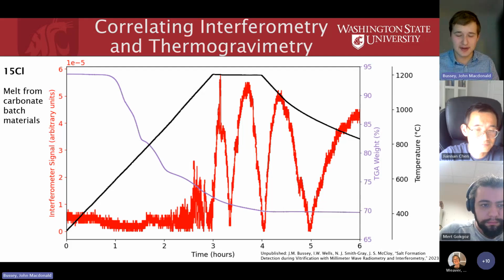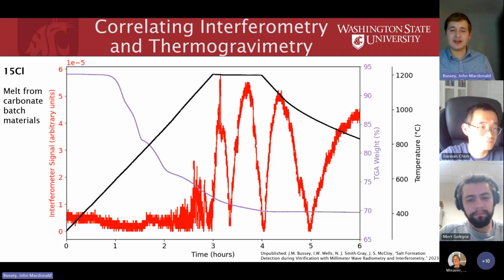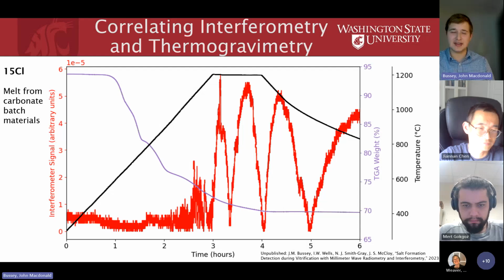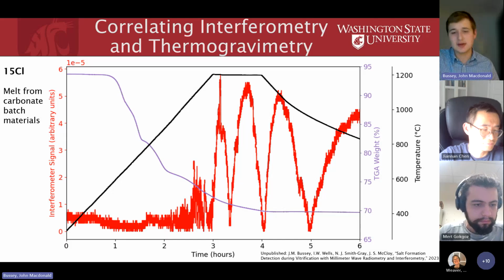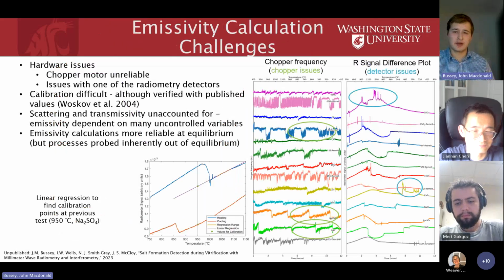We found that the majority of the foaming happens only at the very last 1 or 2 steps of carbonate loss, which again, perhaps this is not too surprising because at lower temperatures, the glass is not fused yet, and so it's not reactive enough to form large bubbles. So bubbles only form at the very end of the gas evolution.